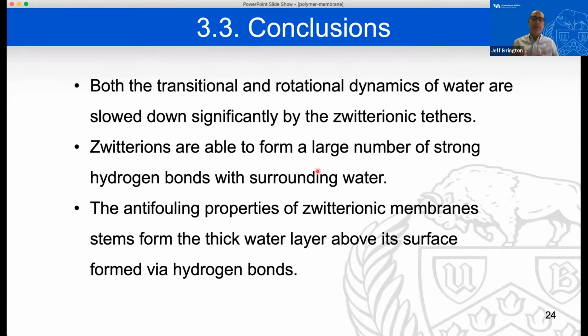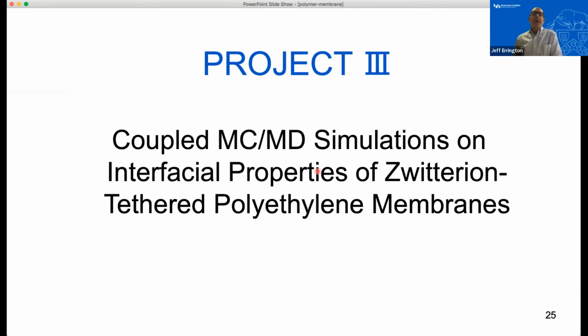And of course, if you make a connection between what we are observing here and what we are observing in terms of the wetting behavior, there's consistency in the sense that those systems that we found to be highly hydrophilic, highly wetting, in other words, the ones that are associated with the Zwitterionic tethers, are the same ones that have the most significant impact on the mobility of water in the vicinity of the polymer tethers. So there's consistency there in terms of what we're observing from both a thermodynamic perspective and a dynamics perspective. All right, the last part here, I'll just spend a few minutes on this.